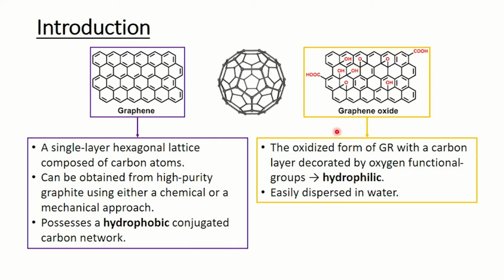Meanwhile, graphene oxide, another two-dimensional carbon material, is known as the oxidized form of graphene, with a carbon layer decorated by oxygen functional groups as a result of oxidation and chemical exfoliation of layered crystalline graphene. Although graphene oxide is similar to graphene, its properties are very different. Graphene oxide nanosheets are hydrophilic in nature due to the presence of oxygen functional groups. Thus, due to its hydrophilicity, graphene oxide is easily dispersed in water. Meanwhile, graphene possesses a hydrophobic conjugated carbon network that makes it easy to be modified by various kinds of functional molecules and nanostructures.